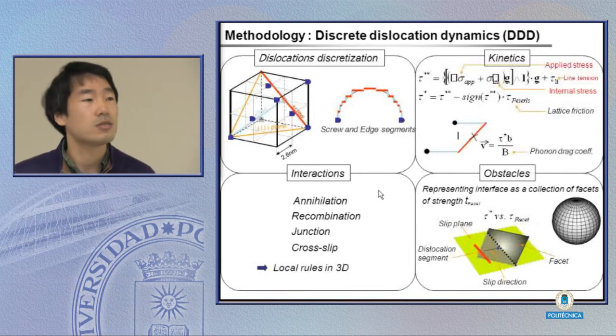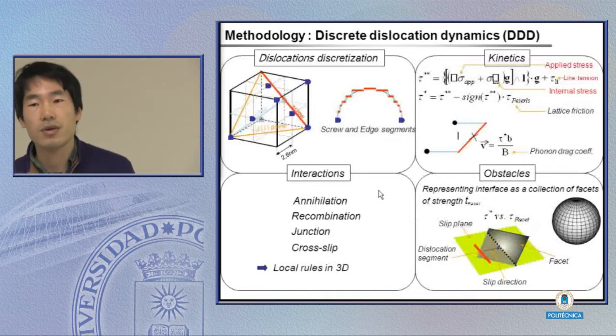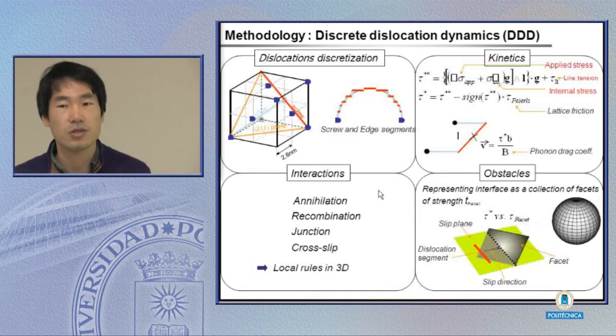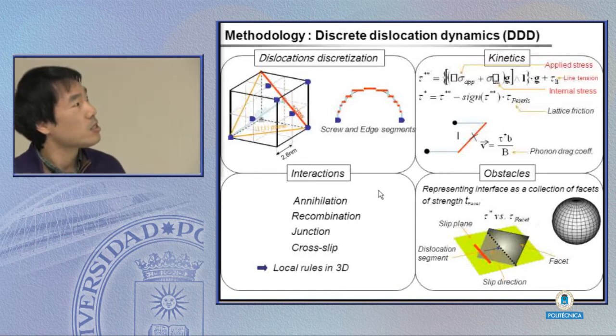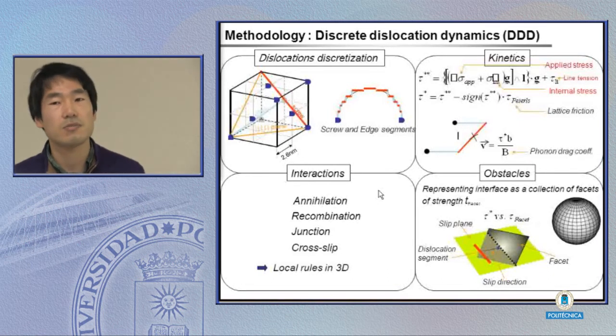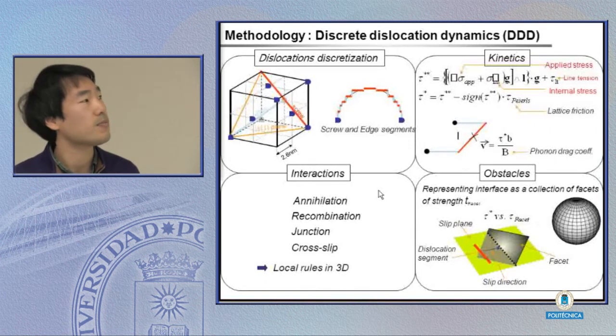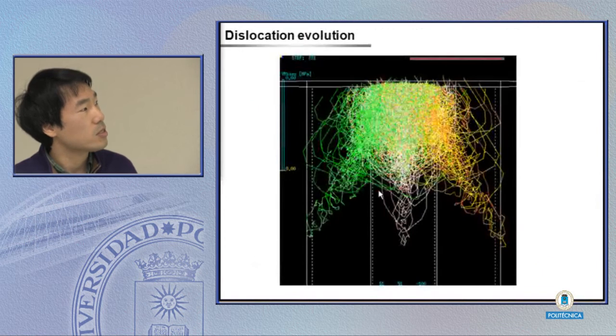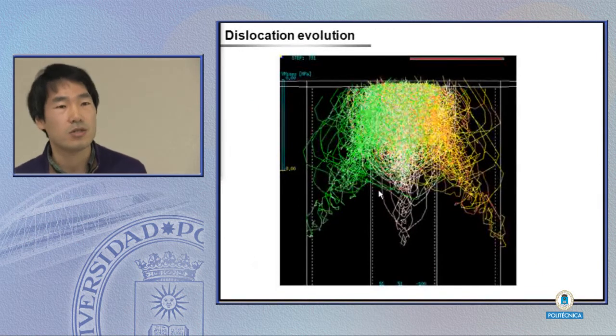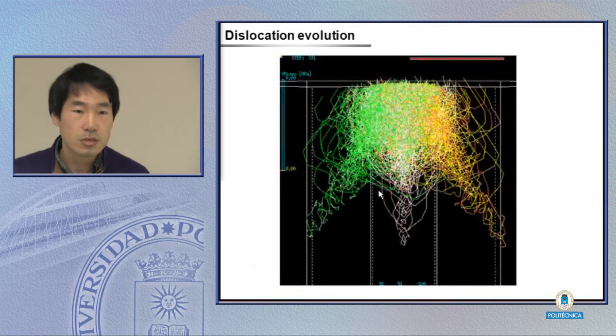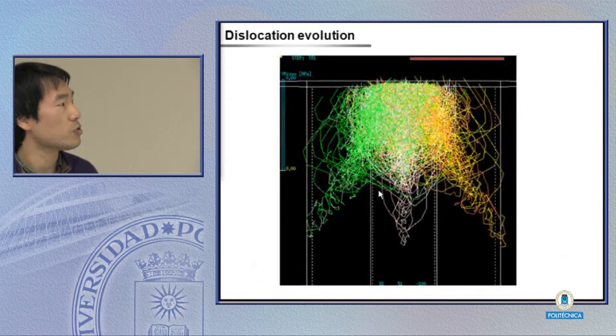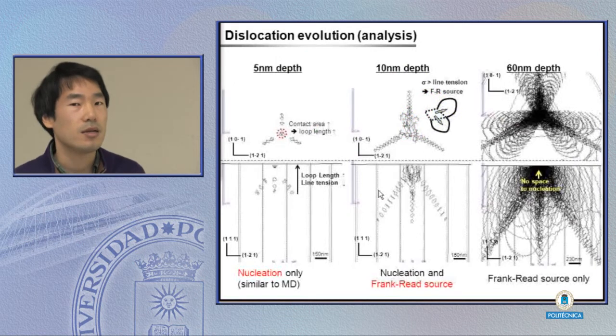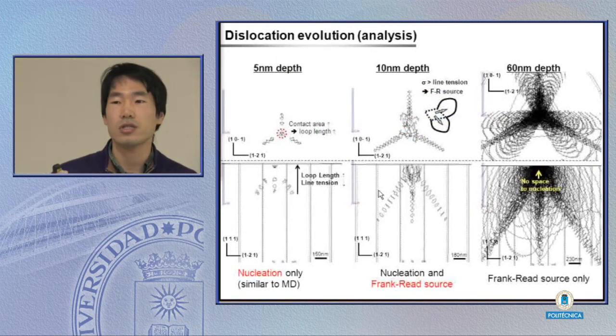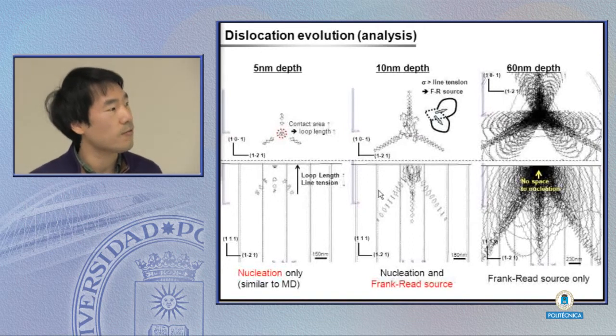And what is the dislocation dynamics? There are many ways to simulate the dislocation dynamics, but in my case, the dislocation lines are discretized by edge and screw dislocations. And each segment can be moved due to the applied stress and internal stresses. And in the dislocation simulation, it also includes the local dislocation interactions, such as annihilation, recombination, junction, and cross-slip. And it also simulates the dislocation interface interactions using the facet algorithms.